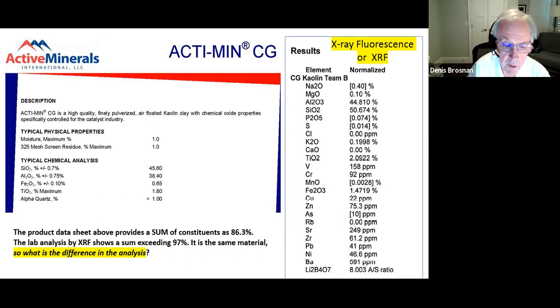You certainly want less than 1% moisture to have a free-flowing powder. That's probably on an as-received weight basis. In this particular material, there's a particle size criterion, maximum amount retained on a 325 mesh or 44 micron diameter opening screen of 1%. So these are some numbers, but I really want to focus on the chemical analysis.